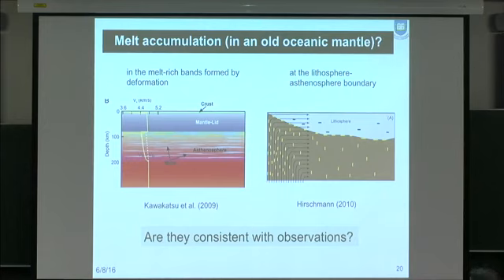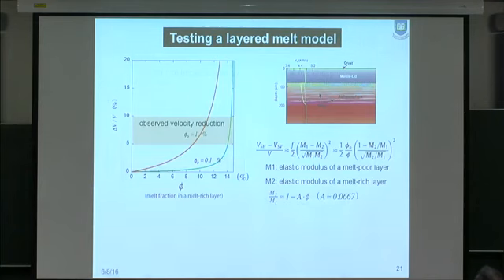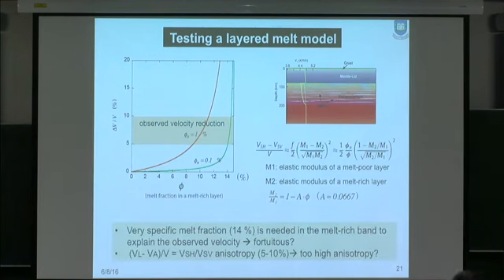So let's check if those models are consistent with observations. For instance, for this layered model to be consistent with observations of a relatively large velocity drop, you must have a very unique porosity in the melt-rich band. For instance, if the background porosity is 0.1, then the porosity or melt amount in the band has to be 14.3. If it's 15, you have a 20% velocity reduction. If it's 13, you have a 2% velocity reduction, away from the observational constraints. So therefore, this model, in my opinion, is really hard to reconcile, unless there is a theory to predict that the melt fraction in the melt-rich band is 14.3.